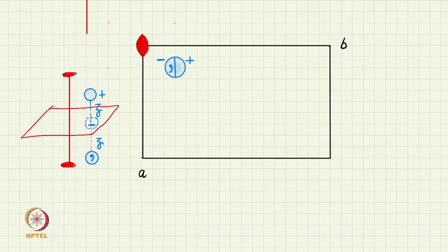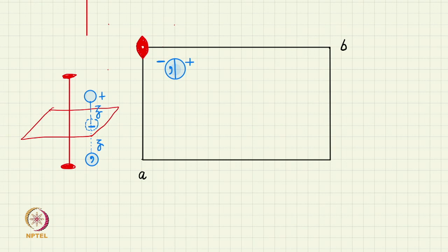A center of inversion is also, if you see the symmetry diagram, shown by a hole in this lens. So, I create a hole. Of course, you know that this particular site symmetry will be considered as 2 by m, because there is a two-fold axis and there is a perpendicular mirror plane, and whenever you have a symmetry like 2 by m, the intersection point develops as a center of inversion. So, that is what is being represented there.